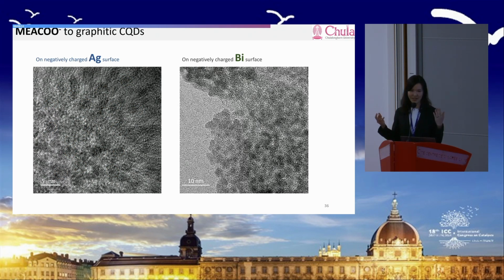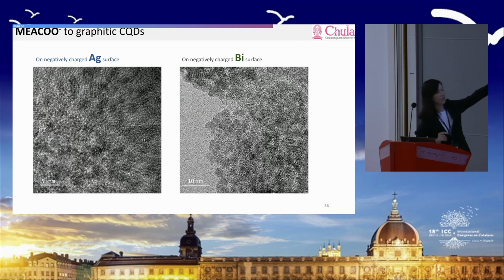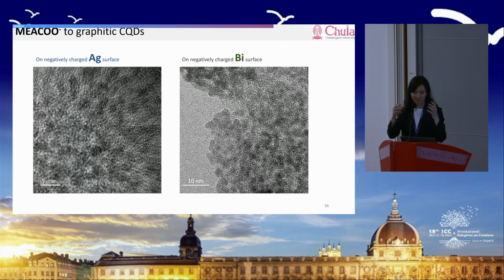We take a look between the bismuth surface and the silver surface. From bismuth, I showed you previously, we can apply bismuth in our MEA CO2 system as well. We see small graphene joined together on the right. On the left, I'm not sure, we see some distortion and some stacking of the small graphene. That's how they shift towards the diamond.